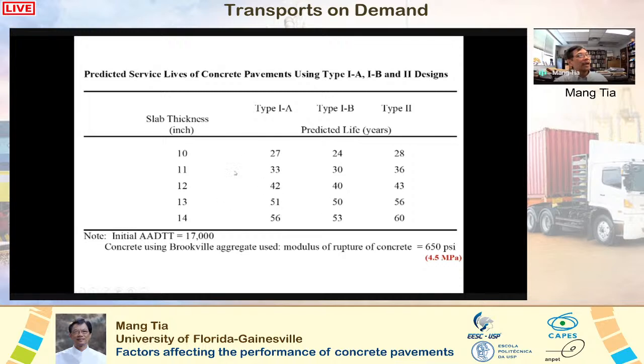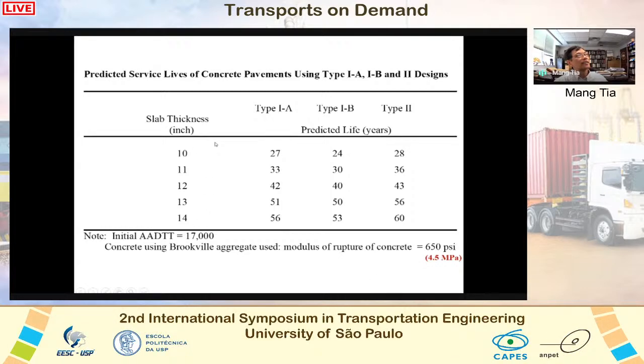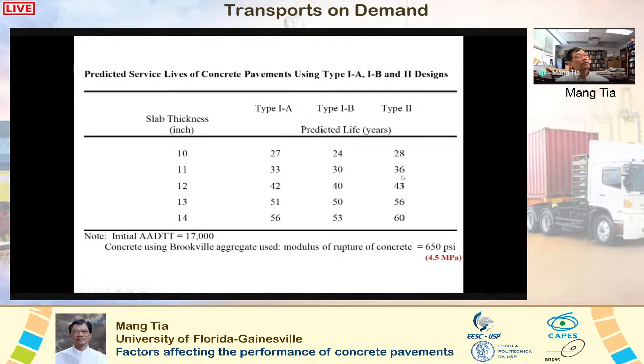Okay? And we use this best aggregate for our concrete. Okay, and so we ran the analysis to see how long it would last, if we have different thicknesses, and here are the different thicknesses. This shows the expected life. Okay, and you can see that we use this good concrete made with this good aggregate. It can be done if the thickness is 13 inches. So here, at 13 inches, the life expectancy is over 50 years for all three designs, and the type 2 is relatively better than the other two. So, but all of them would work.